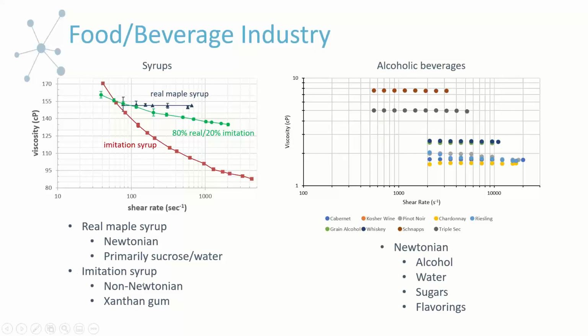However, if you look at the imitation syrup, which does have this non-Newtonian or shear thinning behavior, and you look at the ingredient list, the final ingredient on the list is xanthan gum. And so what we just saw when we were talking about the rheology modifiers is that this is a very high molecular weight, bulky polymer that even in very low concentrations is going to introduce a significant amount of shear thinning behavior and increase the viscosity. So even though it's last on the ingredient list, and thus in there in a small quantity, we can see that it has a huge impact on the rheological behavior of this syrup.